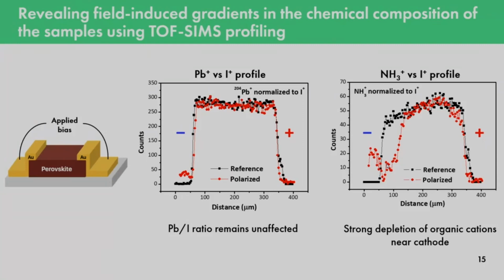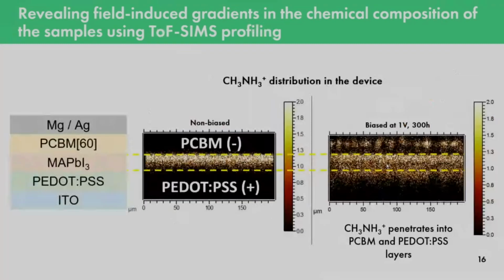And this means that we have a destruction of the organic part near the cathode. Most probably there was some kind of reduction of these organic cations, which led to volatile products that left this kind of film. But at the same time, iodine looks like it remains stable, mostly.